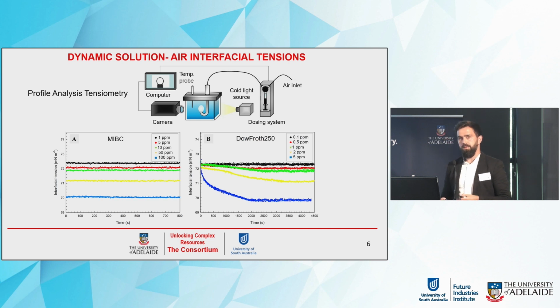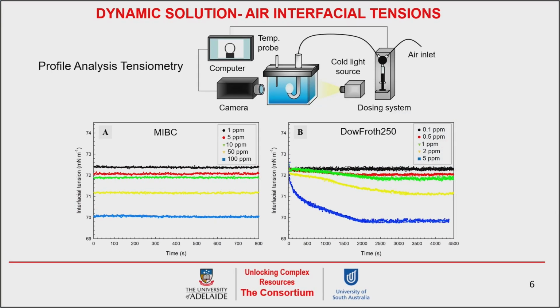So the first step of our investigations was to get interfacial tension values for our frothers, and we wanted to describe as well the adsorption properties by profile analysis tensiometry. And as we can see, MIBC is characterized by instantaneous adsorption as there is no interfacial tension drop over time, while the second frother, which is DowFroth250, is characterized by slower adsorption kinetics because we can observe this gradual decrease in interfacial tension. However, the surface activity of DowFroth250 is much higher because lower concentrations were required to achieve a similar interfacial tension drop. So we can clearly see that we are dealing with two frothers having completely different interfacial behavior, right?